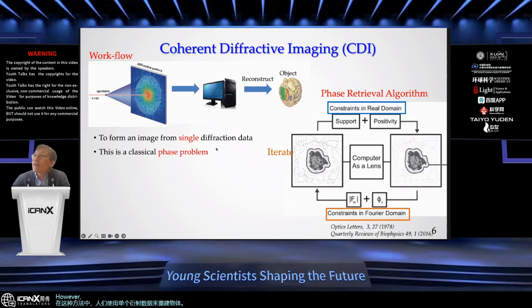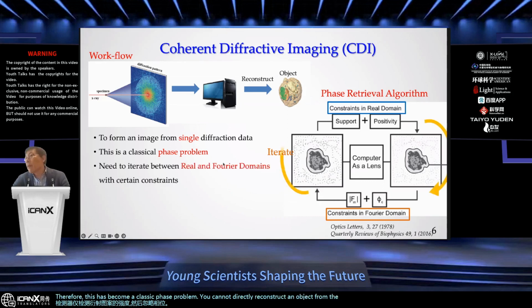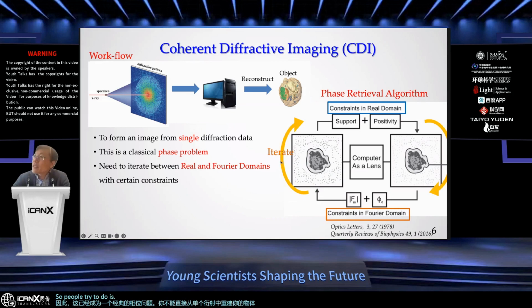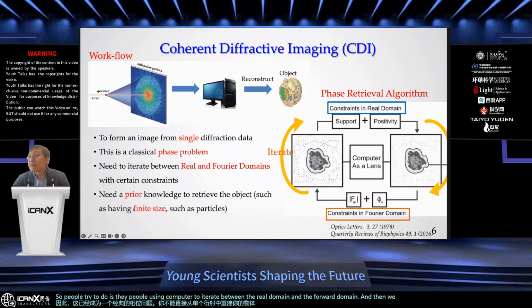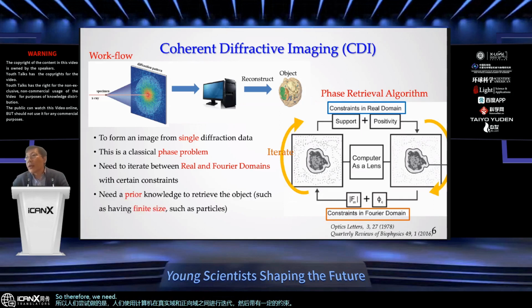However, there is no free lunch, because the detector only detects the intensity of the diffraction pattern and ignores the phase. Therefore, this becomes a classic phase problem. You cannot directly reconstruct your object from the single diffraction dataset. So people use a computer to iterate between the real domain and the Fourier domain with certain constraints. Therefore we need prior knowledge in order to achieve a unique solution of this algorithm. People will consider the object has a finite size, for example, a particle.